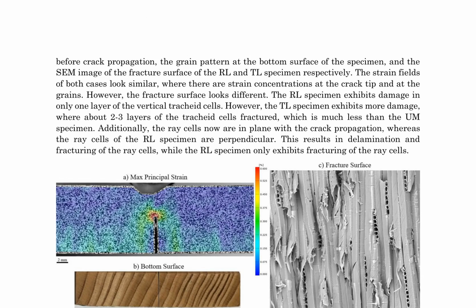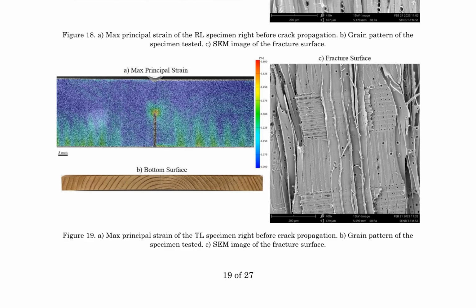In the context of the research on fracture mechanics in wood, the authors present a comparative analysis between radial-longitudinal, RL, and tangential-longitudinal, TL, systems. The study focuses on the strain fields, grain patterns, and fracture surfaces of thermally modified wood specimens. The RL system exhibits damage in only one layer of tracheid cells, with ray cells being perpendicular to the crack propagation. This results in fracturing of the ray cells. In contrast, the TL system shows more extensive damage, involving about 2 to 3 layers of tracheid cells, and delamination and fracturing of ray cells as they are in plane with the crack propagation.